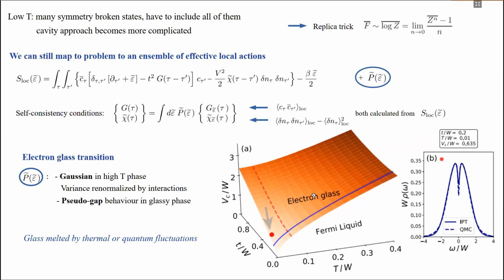Before going further, let me just show you the phase diagram. Here is the phase diagram that we obtain. At high enough interactions, we get an electron glass phase where this field distribution is not Gaussian. This electron glass phase is governed by the interactions, so we always get it if the interaction is strong enough. This glassy phase can be melted either by thermal fluctuations, by increasing the temperature, or by quantum fluctuations, by increasing the strength of the hopping. One other thing that I show here is the density of states at exactly the phase transition. You see a dip in the density of states at the Fermi energy. This dip already shows you that pseudogap behavior is going to happen if we go into the glassy phase, and the presence of this gap is a consequence of the repulsive nearest neighbor interactions.